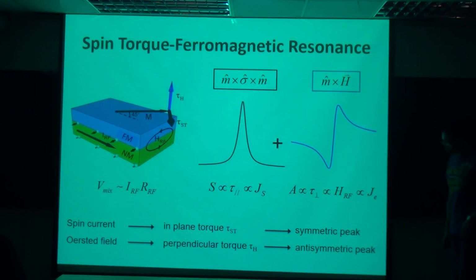And anyway, when you see the FMR signal, you'll see it's a combination of a symmetric peak and an anti-symmetric peak. And these two correspond to the contribution from spin current and charge current respectively. So after getting the data, you decompose the signals into these two terms. And by comparing the ratio of these two, then you can get the spin Hall efficiency, or the spin Hall angle. At least that's what we called it at the time.